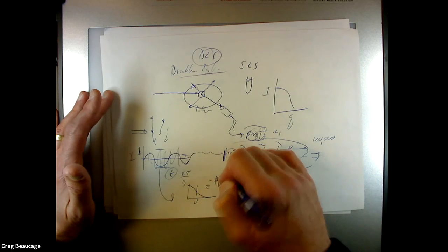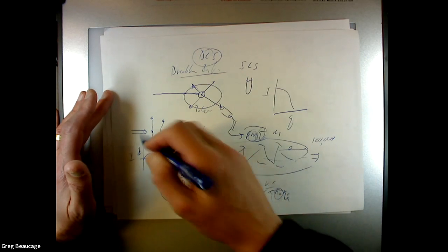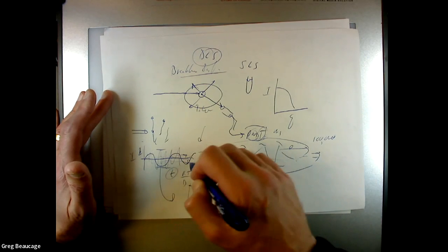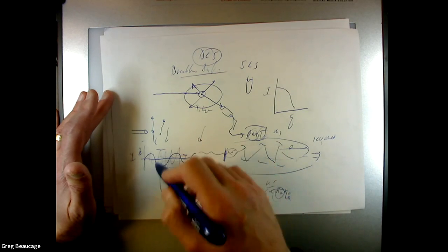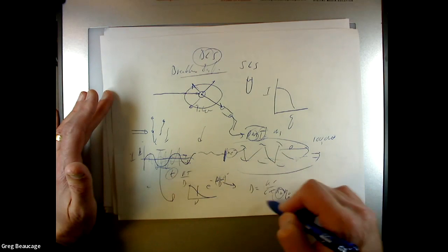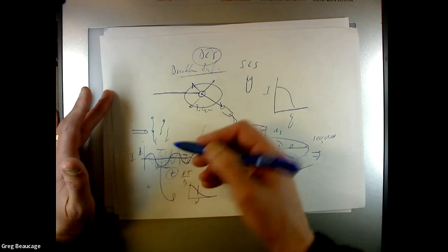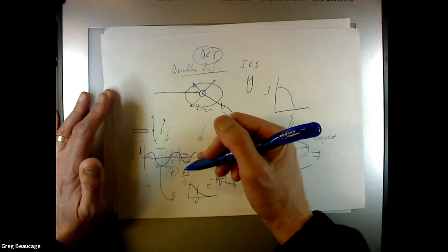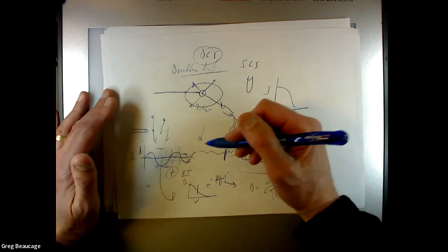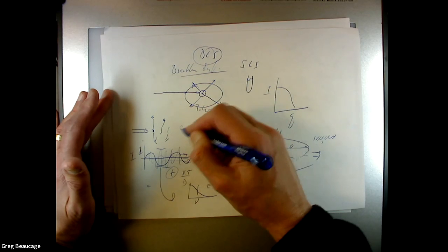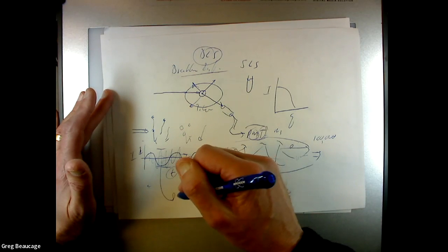This one's much easier. This one is just stick the stuff in the solvent, make sure there's no dust in it. Then push the button, you'll get this noise pattern. Then it does the Fourier transform for you, and it spits out the hydrodynamic radius. So you can put anything in this. You can put milk into it. We do the lab for milk. It's got colloidal things flying around. You can get a size of them pretty easily. Doesn't take long. It's absolutely the simplest thing to run.